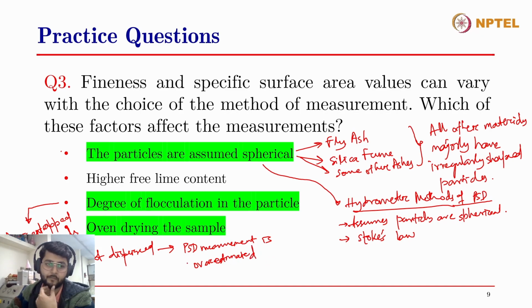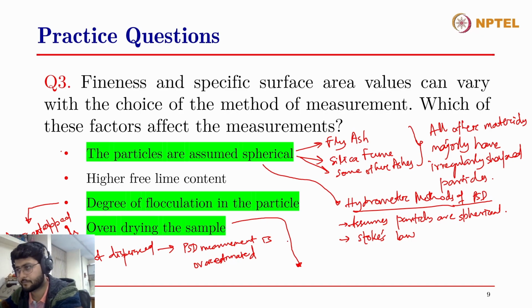Overestimated, right? And then the third is oven drying the sample. If the sample has some moisture in it, then this moisture will also be entrapped in the air that is entrapped within the flocks of the particles, and that will get released in these measurements. That might also affect, depending on the specific gravity of the fluid, let's say in the hydrometer method as well, the type of fluid that you're using to measure the particle size distribution of your cement and so on. That will also affect the measurements.